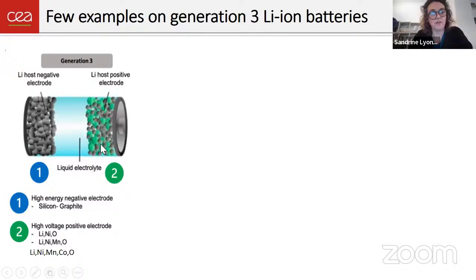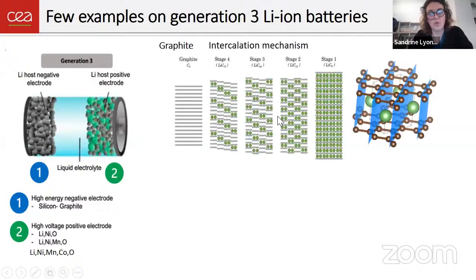On the side of the positives, you have at the state-of-the-art some nickel, manganese, cobalt layered oxide materials, for instance. And at the anode, that's what I'm interested in, you have graphite, which is a historical material that is enabling to store 1 lithium per 6 carbon, as you can see here in its most lithiated phase. And this is an intercalation mechanism. So basically, what you do is you put lithium ions in between the graphene sheets, according to some staging process.